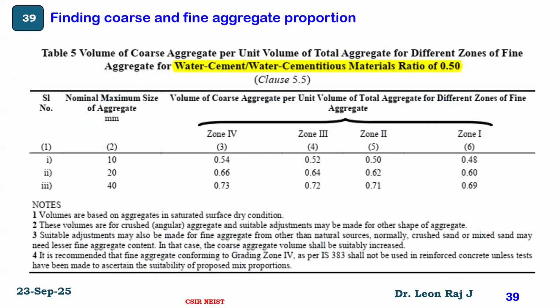For a fixed value of water cement ratio, water by cement ratio is 0.50. These values are given for different zones: zone 1, zone 2, zone 3, and zone 4, that is different fine aggregate. The coarse aggregate by total aggregate ratio is nothing but CA by TA, where TA is total aggregate and CA is coarse aggregate. For a maximum nominal size of aggregate of 20 mm, and for zone 2, your CA by TA value is 0.62. So what is meant by this 0.62? That means 62% of total aggregate is coarse aggregate. The remaining 38% is fine aggregate.